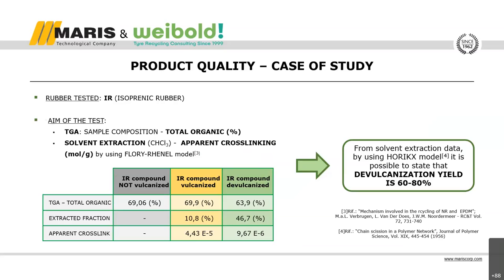The data obtained allowed us to get the apparent cross-link, which is a direct indication of the level of cross-linking of the sample. With the devulcanization process, in this case, we have reached a value of apparent cross-linking 10 times lower compared to vulcanized rubber. Now, summarizing from the extraction data by using the Horikx model from the literature, it is possible to state that the devulcanization yield is between 60 and 80%, and this is a very good result.